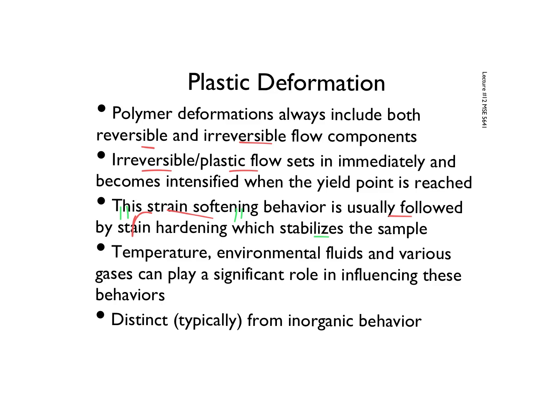And one other thing that's important here is that these are plastics, and they're here at room temperature, which normally for metal ceramics isn't a big deal, but for polymers there are lots of things in the environment that can change that. Environmental fluids, we already talked about temperature, and various gases can play a significant role in influencing these behaviors. And this is especially going to become obvious when we talk about crazing later on. We have plastics that under normal conditions, they don't craze under load, and then you bring some acetone into the room, and suddenly they start crazing because the acetone affects the plastic. All right, and so these are normal things with plastics, and so this is distinct, at least normally, from inorganic behavior, except for some glasses and things like that. It's not normally something that we consider to be significant when we talk about metals and ceramics.